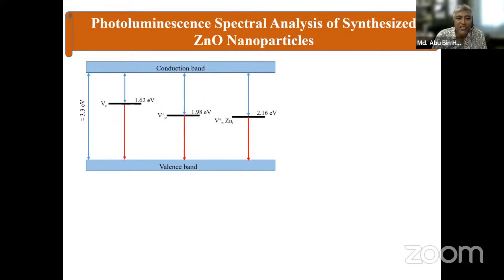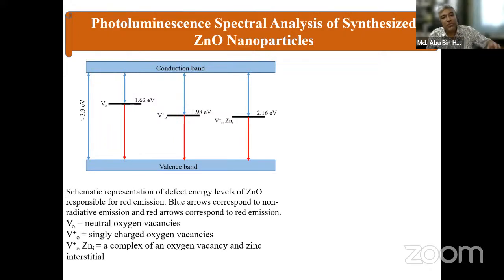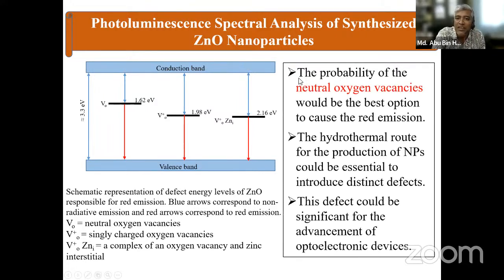And if we check the photoluminescence spectral analysis of the zinc oxide nanoparticles, we can see that the conduction band and band gap showed some changes, because the schematic representation shows the defect energy levels of zinc oxide responsible for red emission. Blue corresponds to non-radiative emission, and red shows the corresponding red emission. And since this level is being changed, we can actually comment that the probability of the neutral oxygen vacancies